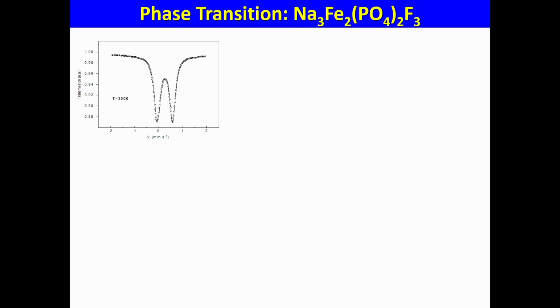So we have a chemical sample, this fluoride, and we were rather lucky because the lines were very well defined. So, a good sample. You can easily estimate the isomer shift, 0.3 at room temperature, iron 3+. Okay, the chemists were satisfied.